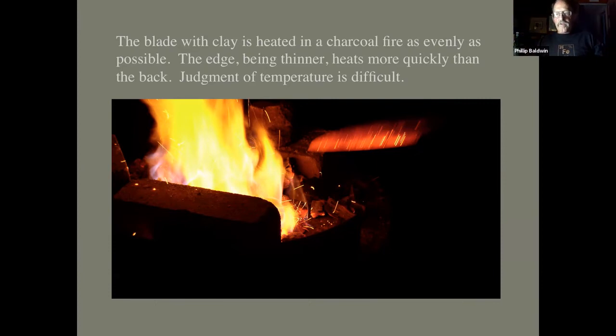The Japanese quench in water because their steel is basically just straight iron and carbon. Very shallow hardening. And so they really need a water quench to get it up to the hardness that they want. Plus they're using what we would call a medium high carbon steel, about 0.6. And this is very high carbon steel, probably more like about 1% carbon. Next slide.